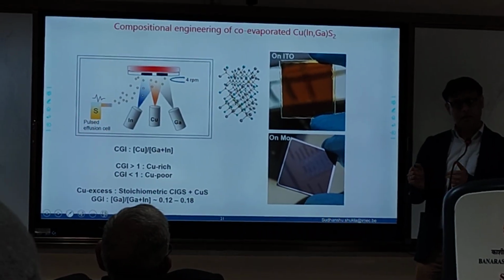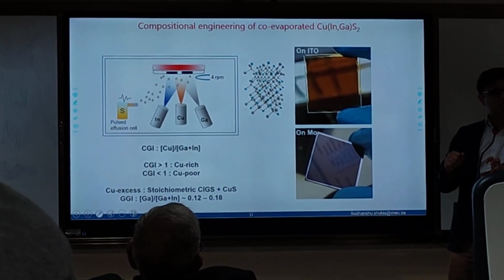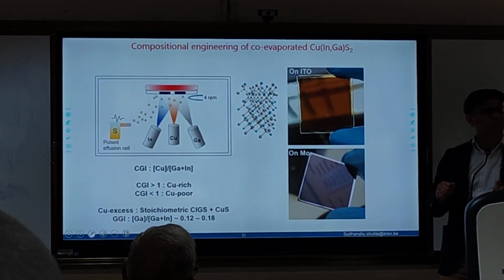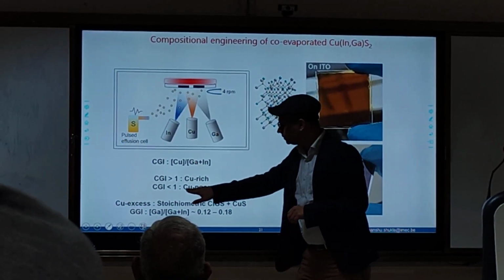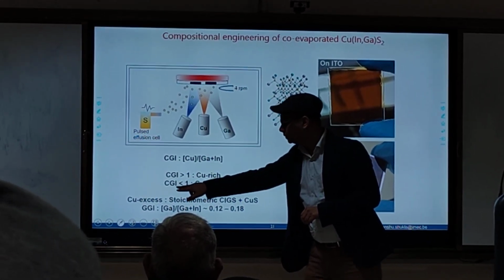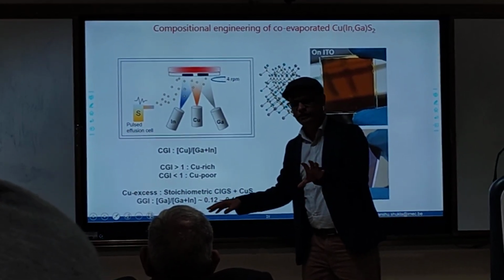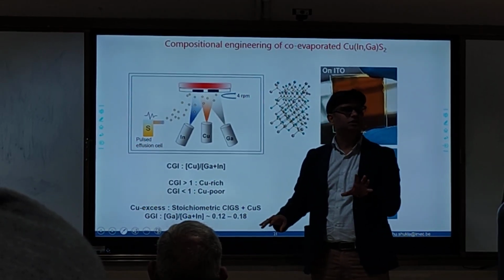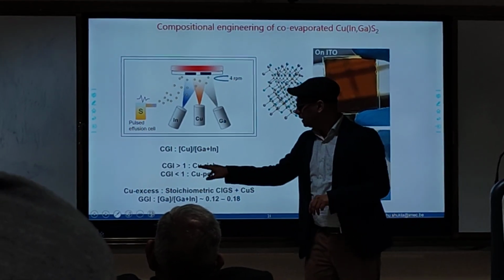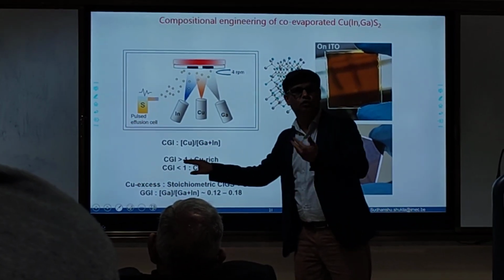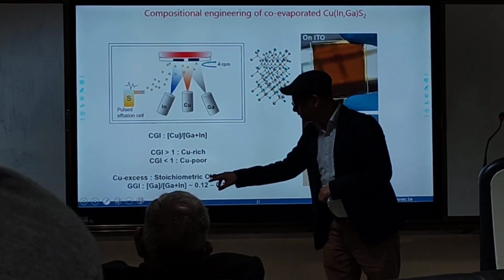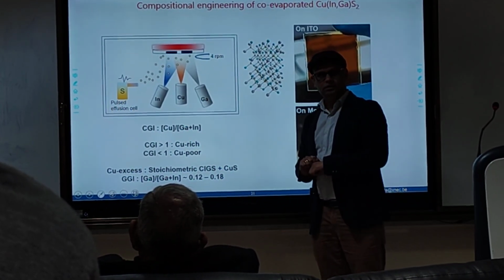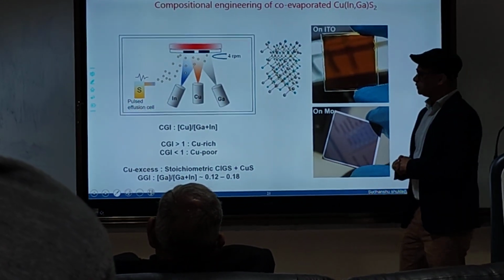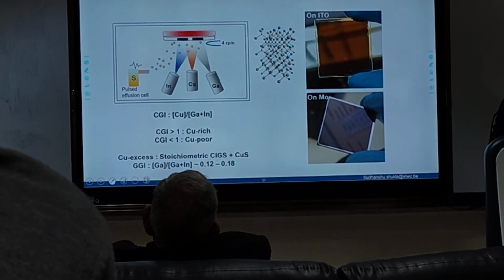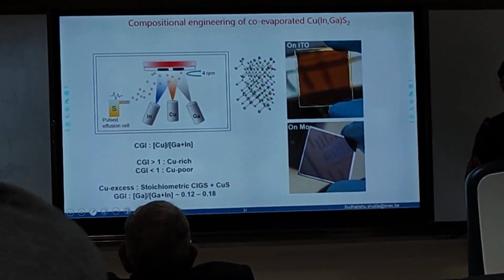So if the phase diagram allows you to make a semiconductor with a certain deficiency of a molecule, you can do so. I made this copper poor, so you see CGI, which is the copper over gallium-indium ratio. Roughly, it tells how deficient in copper your film is. I also made a copper-rich film, which has excess copper, and it eventually makes copper sulfide. Okay, is everything clear? So the goal here was to introduce this copper deficiency and see if the material behaves